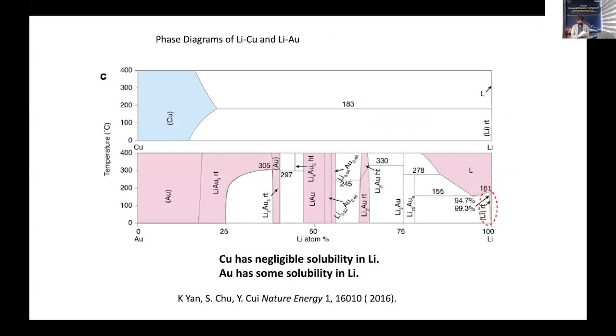If you look at the top, it's between copper and lithium. Bottom is gold and lithium. Look at the most right-hand side of the phase diagram. Copper has no solubility in lithium, but gold has solubility, the tiny zone to the right.